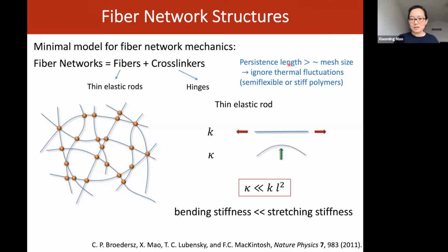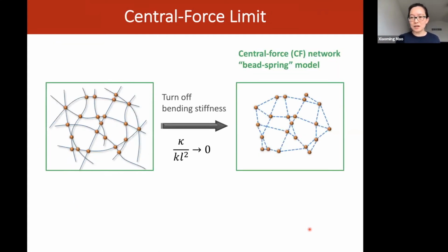Okay, so when you make this simple assumption, you will immediately see that for each elastic rod, each fiber, it's much harder to stretch them than to bend them. So we are almost always in the limit of bending stiffness much smaller than stretching stiffness for each fiber in this network. Then you can consider the limit of completely turning off the bending stiffness and turn this fiber network into a central force network. So the mapping is simply that each cross-linking point turns into a mass point, and each fiber segment turns into a linear spring that connects these points. So I just turn this into basically a bead and spring model. Central force really just means that the interaction between the two mass points only depends on the distance between them.